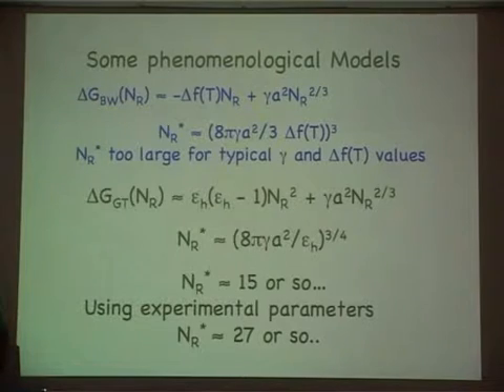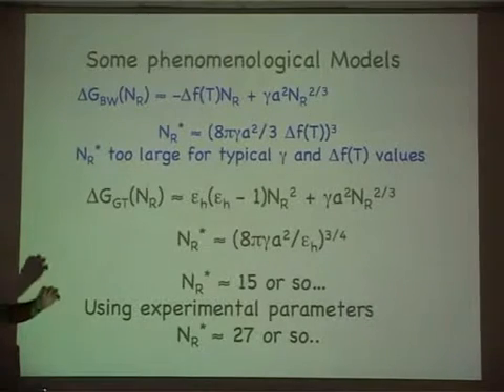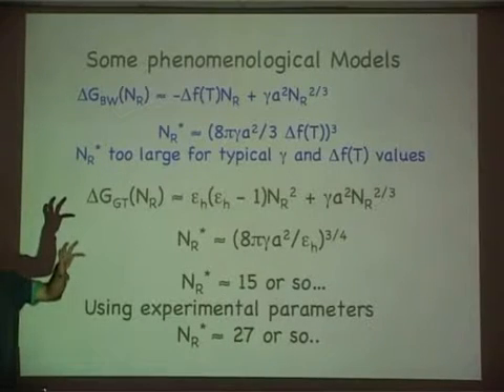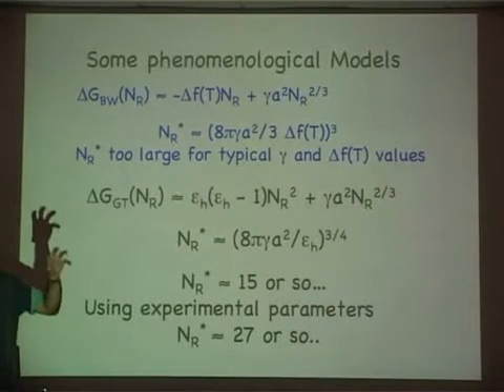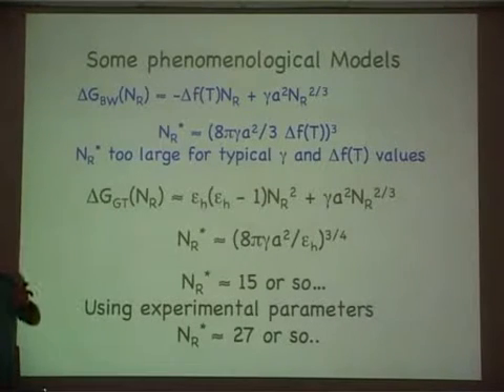If I create, yes? What value, I mean, how do you define gamma over here? What values do you put while trying to calculate NR star? I'll tell you the value and I'll tell you how it's obtained. These are from experiments. The value is 25 to 75 calories per mole angstrom squared. The way it's obtained is to ask, you transfer an amino acid residue, which has a dimension roughly R, from one condition to another condition, say from some organic solvent to water, and you ask, what is the free energy cost of transferring that? And from there, you obtain this surface tension value.